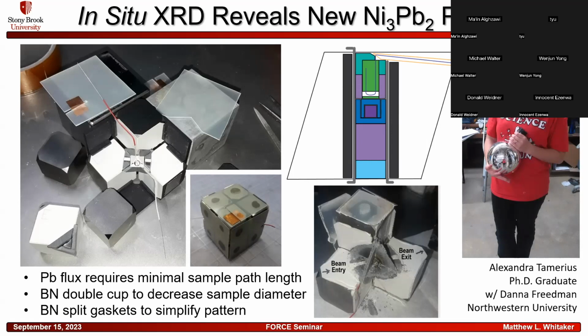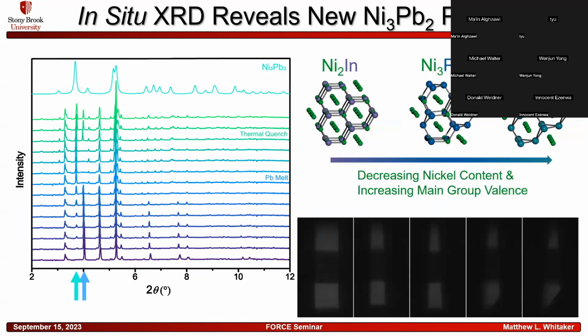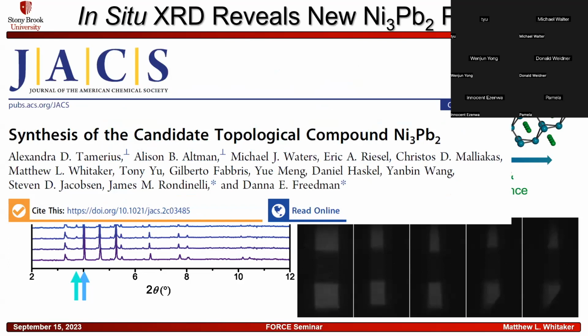And pictured at the right there is Alexandra Tamerius, who at the time was a PhD candidate. She's the first PhD that graduated from experiments done at the NSLS-II, so that was pretty cool. You can see here that as we increase the temperature, the lead melts out, and then after we have the thermal quench, we see that there's a new phase that forms. As we decrease the nickel content and increase the main group valence, we can see the structural changes shown at the top right here. And the bottom left appears a little bit darker than I had intended, but it shows the change in size and shape of the sample as the experiment goes on. And this information was published in JACS in 2022.